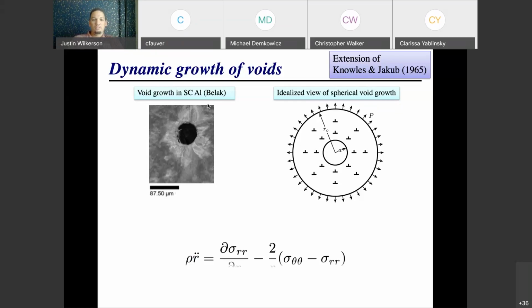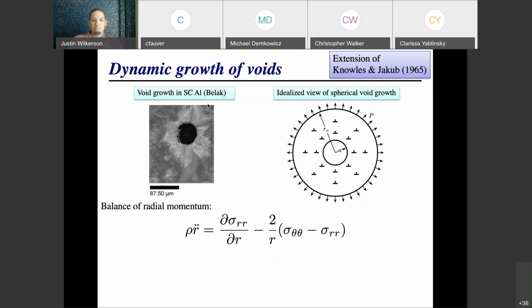Okay, so the simplest way that we can model that is by first considering the balance of radial momentum of a spherical shell, which is given by this equation here. You have rho being the mass density, r being the radial coordinate, sigma r being the radial stress, and sigma theta theta being the hoop stress.